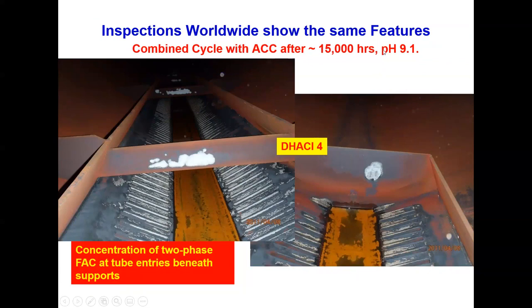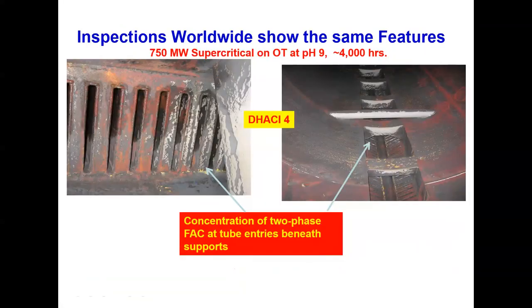So this is after some period of time operating at a pretty low pH here. And you can see these extensive white areas, which are the FAC at the tube entries and on the cross members as well. And there's usually a concentration of this corrosion underneath the cross members, as you can see here. Similar sort of thing for a fossil plant. This is a supercritical unit, but again, after some period of time operating at a relatively low pH, you can see the white FAC damage here, concentrated over on the right hand side underneath the support structures, and then quite a lot of damage on the actual support structures themselves. And so this is basically what is seen everywhere, pretty much the same.